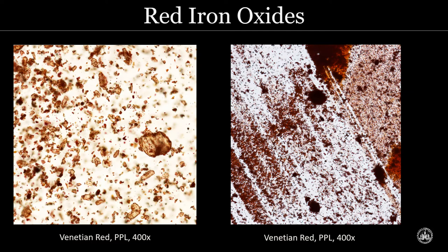Meanwhile, on the right, this sample appears to be, I believe, a synthetic hematite. All of the deep red particles are very, very fine. They have a very similar size and shape, and it's very pure. We don't see any of those associated colorless minerals we saw in the sample on the left. Yet both are marketed as Venetian red. So these are modern pigment samples, but the same thing was happening in the 18th century.